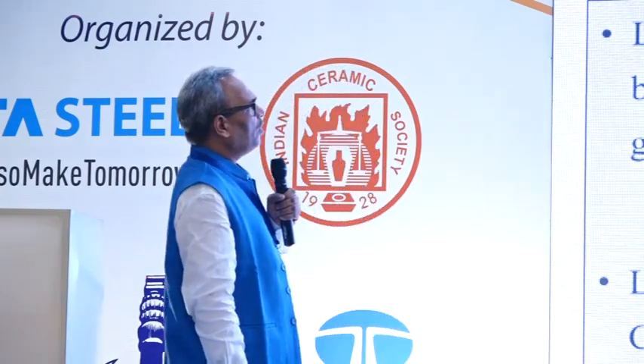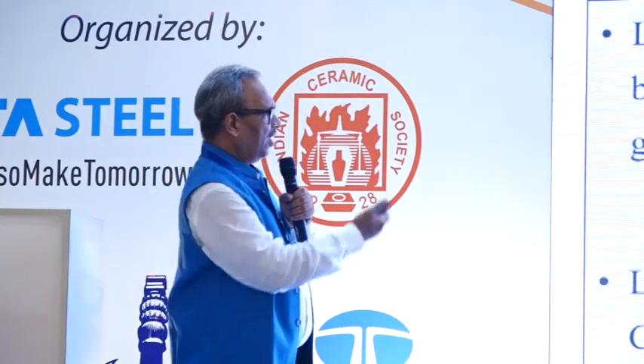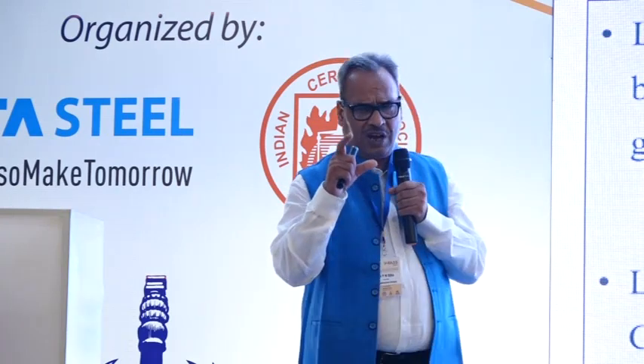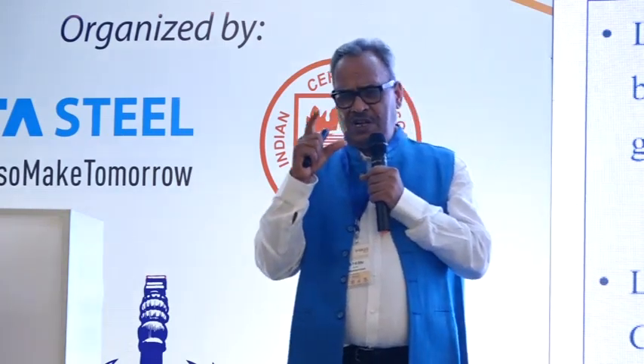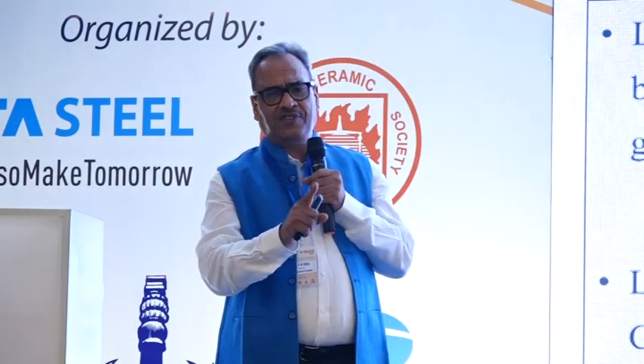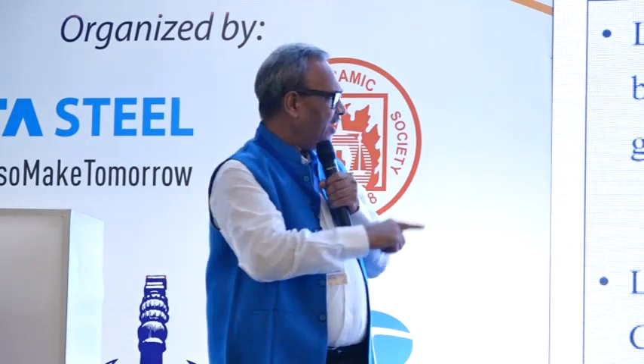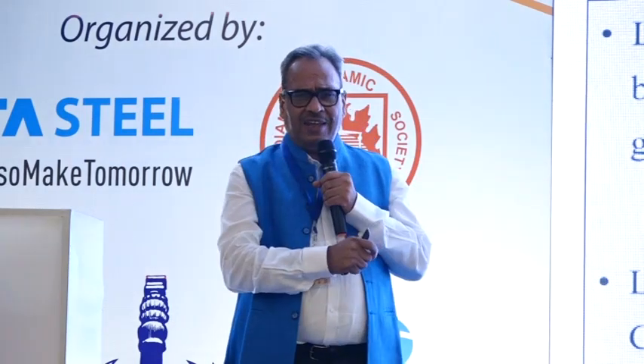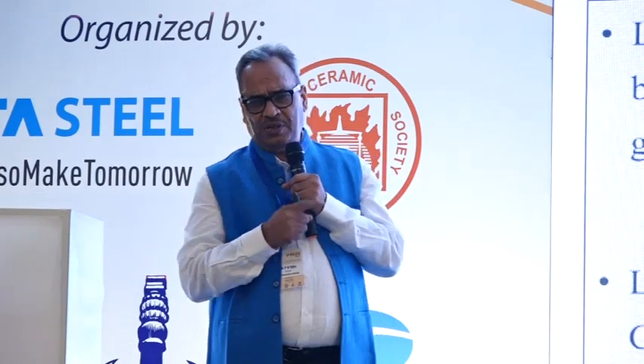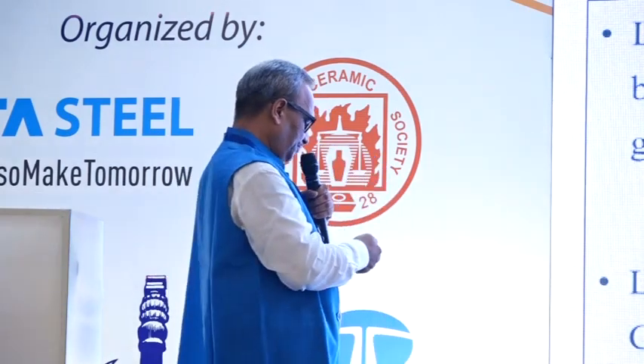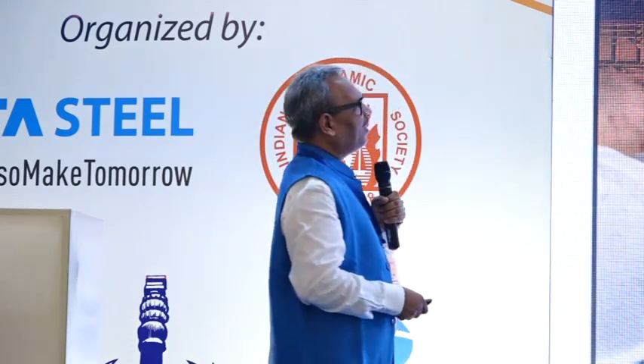So now the recommendation from the industry is that the combined composite slag, meaning BF slag plus LD slag, should have at least 85%, which is being recommended for that. And specifically, LD slag should have more than 40% of the amorphous content. Now we visited the LD slag plant at JSW, of course, to see what can be done with the LD slag.